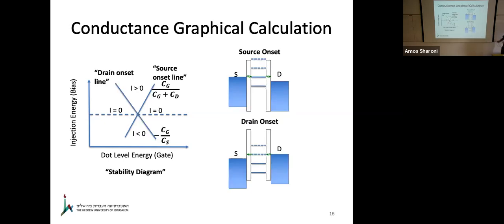You can also show that there is a drain resonant condition where current goes backwards through an energy level resonant with the drain. And now you have these two diagonals, zero current here, positive current on this side, negative current on this side. And this shape is called a Coulomb diamond. The slopes here, the source onset slope and the drain onset slope, are determined by the capacitances in the system. That means that once you've measured everything and you see these diagonal lines in your measurement, you can determine the capacitances in the system.